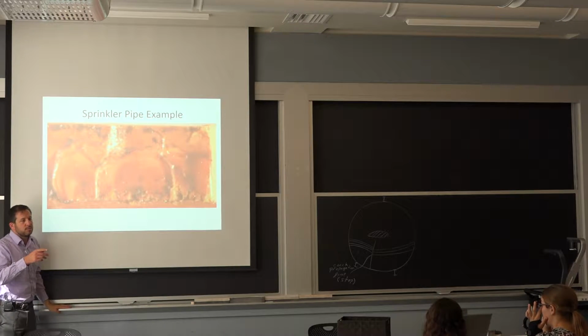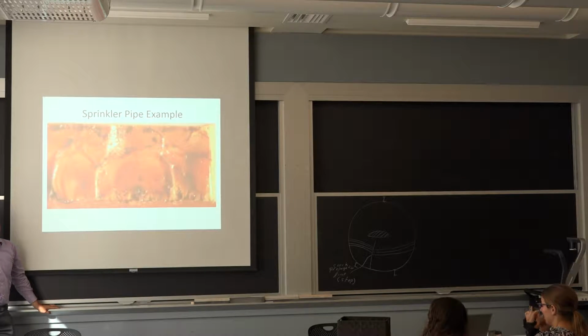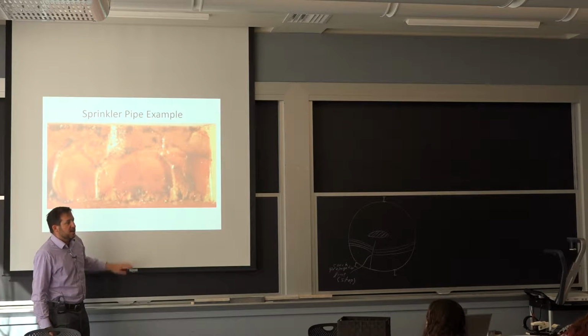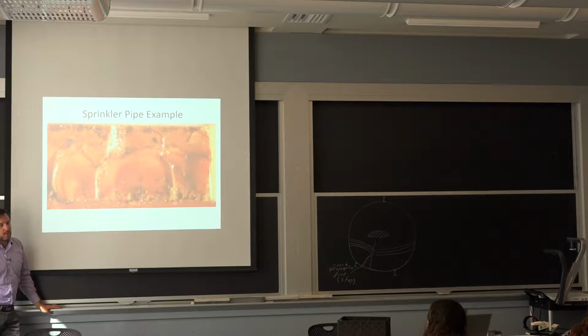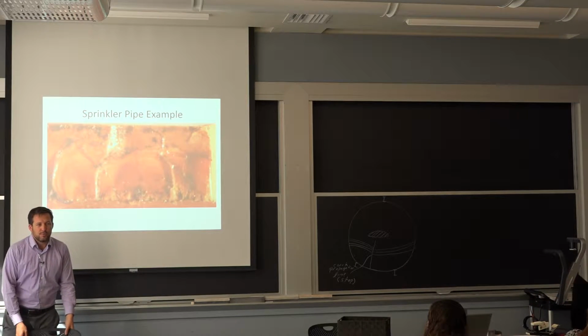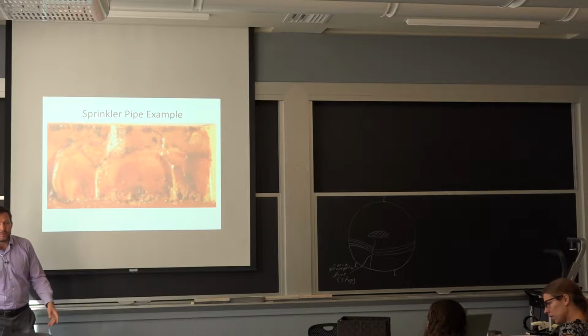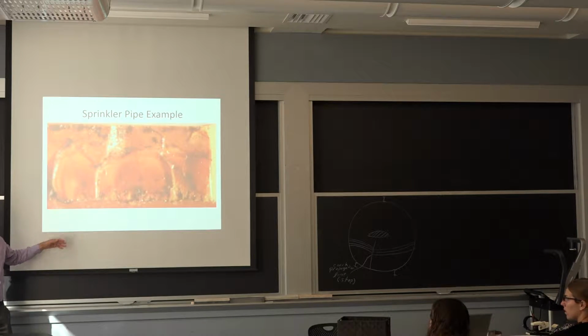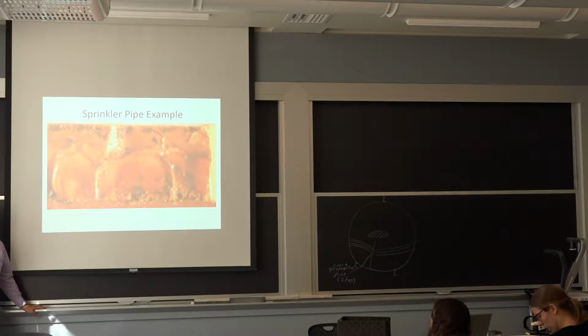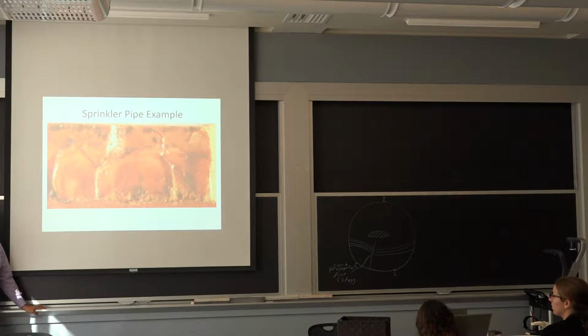So on that fracture, what you'll see is a lot of individual initiations that are spaced maybe 3 millimeters away from each other, approximately. So what does that tell us? Tells us that the problem is not one inclusion, right? If we had one inclusion, we have one crack and it will just grow and cover the space. So initiating was very easy, and most of the time was spent in actually growing that crack through the wall.